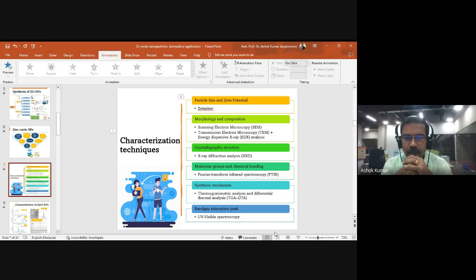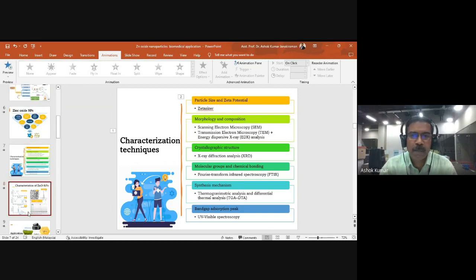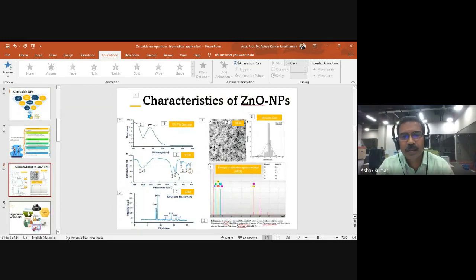Then the band gap absorption peak is measured using UV spectroscopy. And nowadays, for surface functional nanoparticles, they use X-ray photoelectron spectroscopy as an instrument to confirm the surface properties of a prepared material. That is called X-ray photoelectron spectroscopy. So these are some pictures related to the characterization of zinc oxide nanoparticles.